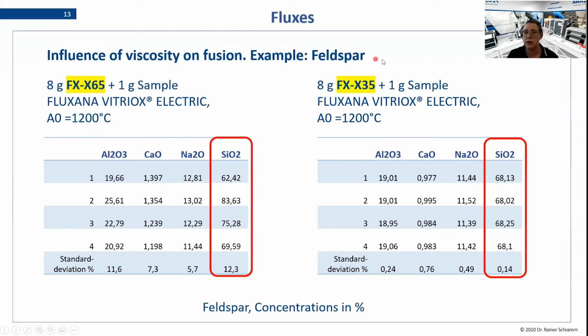And then we did the same sample, the same dilution, same machine, same program, but with another flux where we are having a higher part of lithium metaborate and a lower part of lithium tetraborate. What we can see in the results is that the result for silicon dioxide and also the other components that we looked at with the FXX65, so more tetraborate, is very poor. The standard deviation is very poor, and we can see we have results from 62% to like 84%. And this is just not usable. This analysis is just not usable.